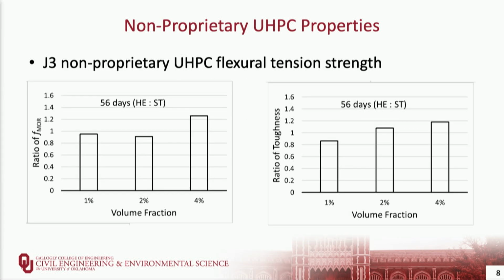Here, my slides got out of order. But if we look at flexural tension strength, we have a ratio between the hooked fiber and the straight fiber specimens, and we see that for the most part we get a little less flexural strength with a hooked fiber, but we are able to absorb more energy if we look at the toughness on the right side there.